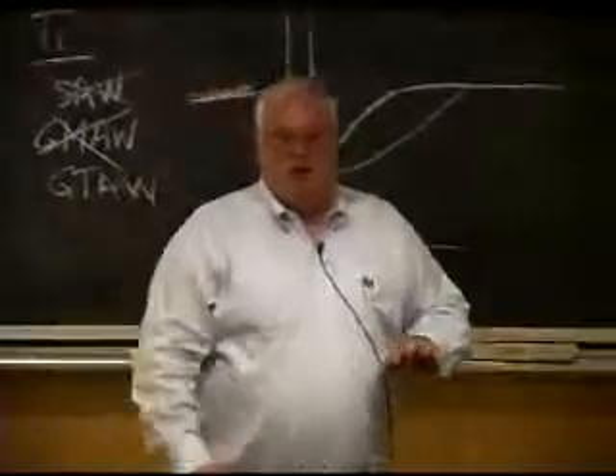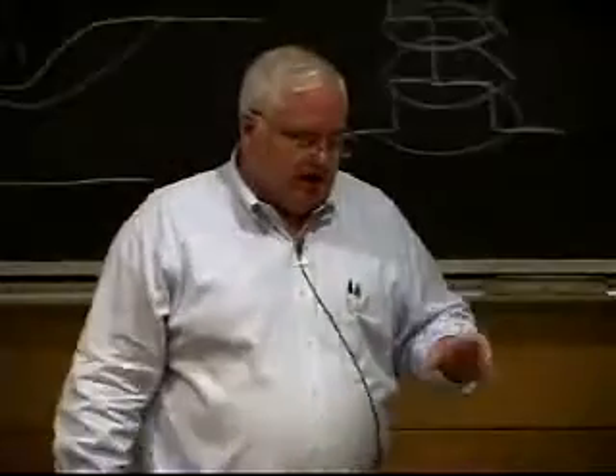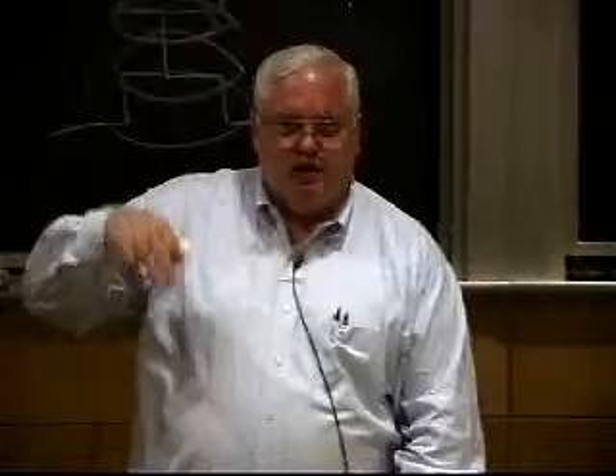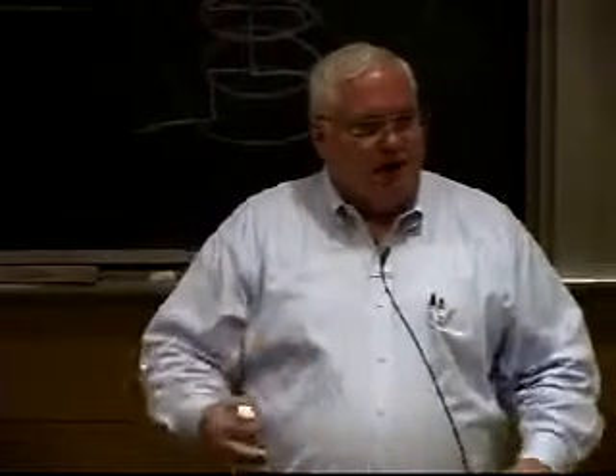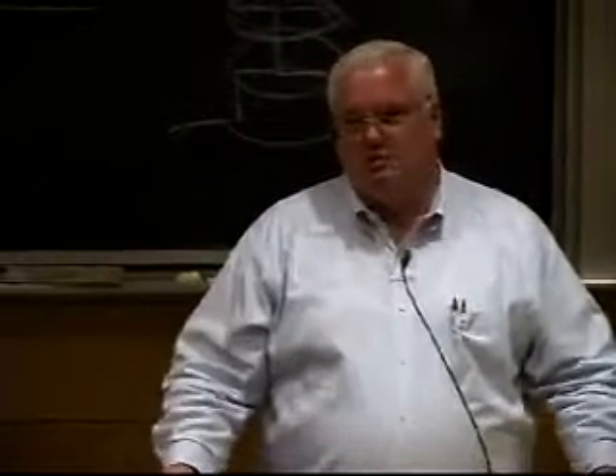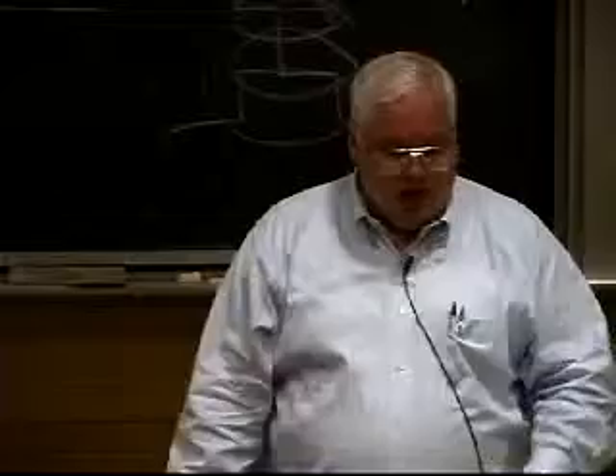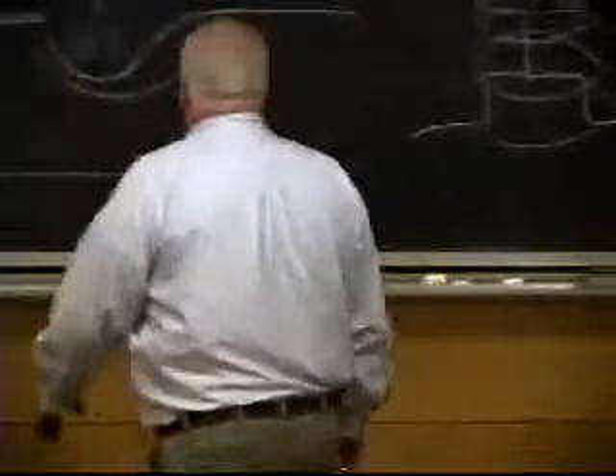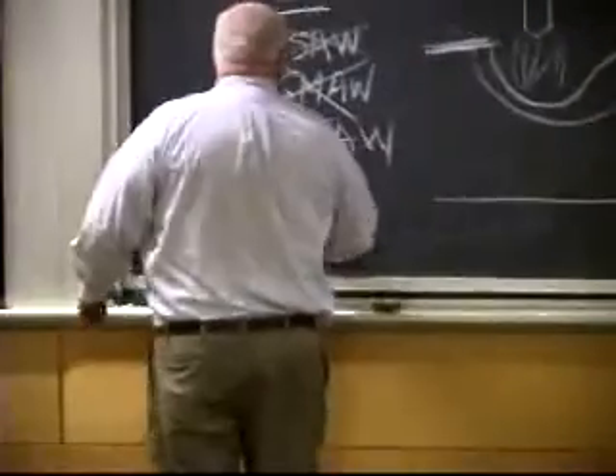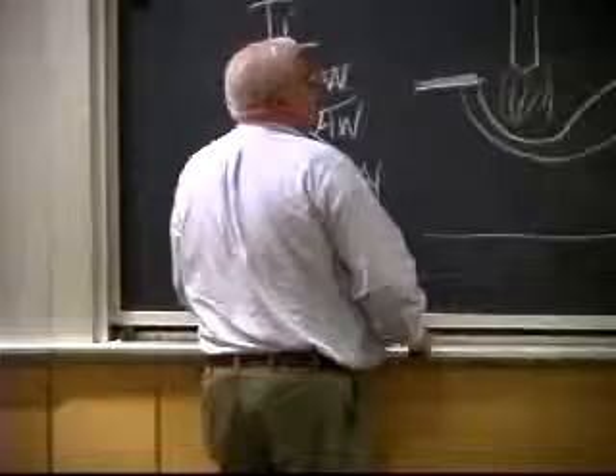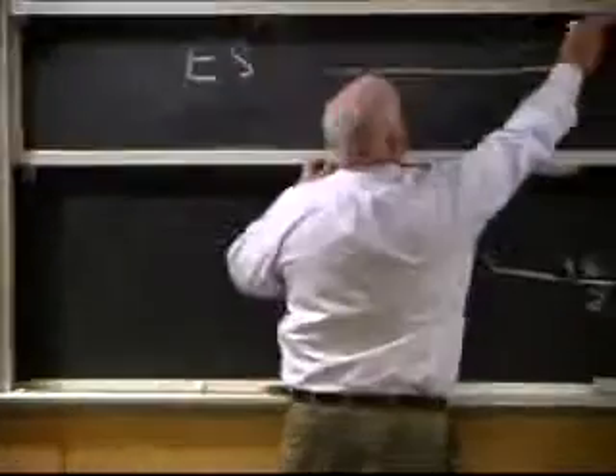You put hardly any on, and without getting into all the details right now, you can get very deep penetration, very big weld beads, 1,000 amp currents. And so you can weld heavy section titanium. That was one thing. That's one way they used to do it. Another was electro slag.